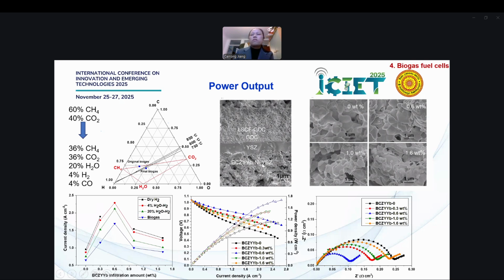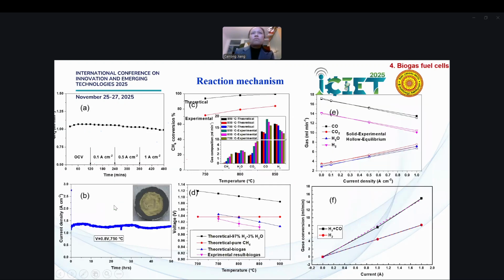And we designed a cell with a similar structure with dense electrolytes and porous anode and cathode. So we really get a good cell performance, also using biogas and even hydrogen. It's up to 2 watts per square centimeter. And by that, we thought about how these cells react in biogas, why it can give a good cell performance, because, you know, this is a nickel cell. Nickel cells usually are not happy with sulfur. We tested and it seems the cell is protected by the infiltration of a proton conductor that we have used in this cell.